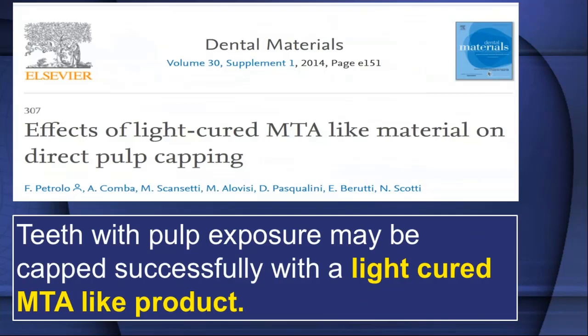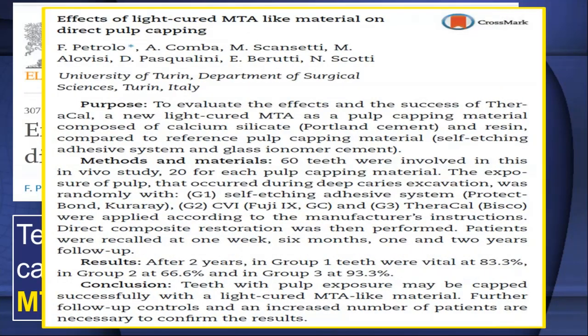And look at the clinical studies. This is again Dental Materials, from 5 years ago, a published article. The research was done at the University of Turin, and they looked at direct pulp caps, using light-cured MTA. They're talking about TheraCal. And here are the results. They had 60 teeth, 20 in each group. Group one had pulp exposure treated with an adhesive system from Kuraray. In group two, they used Fuji IX from GC, a glass ionomer. In group three, they used TheraCal LC from Bisco.